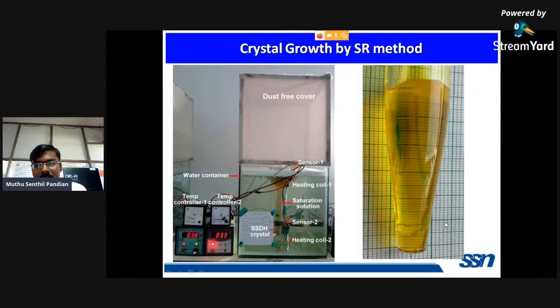So in the SR method also, we have used it under identical conditions. We have grown the crystals in the conventional method and in the SR method also. So in the SR method also, we have prepared the several times recrystallized material and we have poured the solution. After 1 or 2 centimeters of growth, depending upon the solubility of the material, the impurities are accumulated at the top of the glass sample.